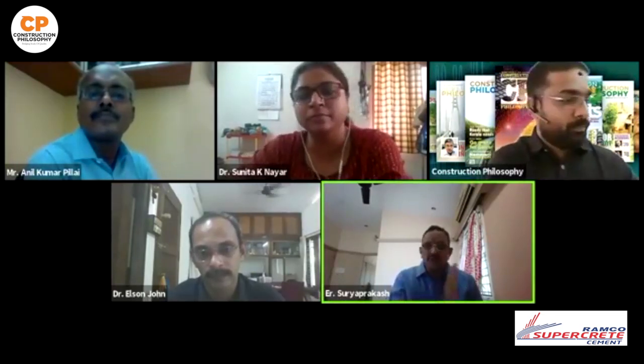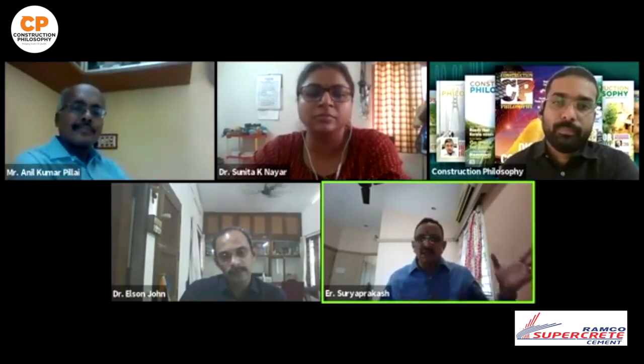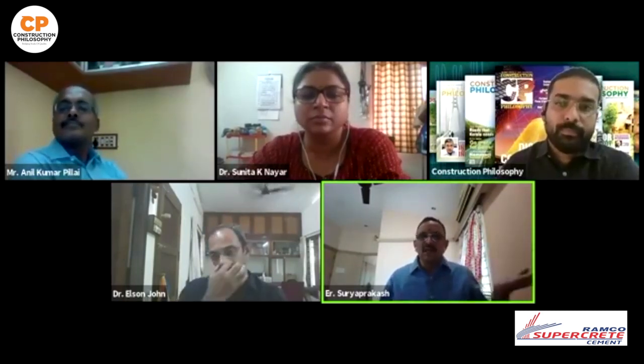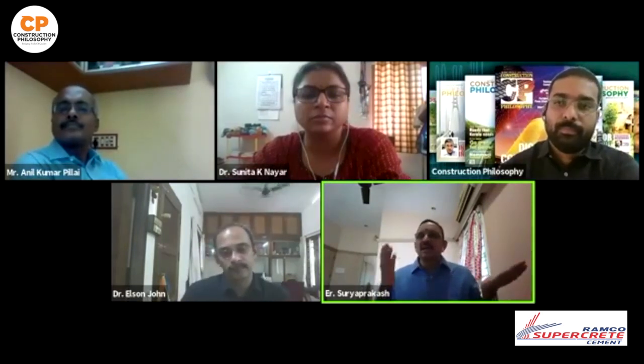Mitigation of cracks is to prevent them. That means follow the quality process. Even if you follow the quality process, the problem can occur because of a mismatch between the environmental conditions assumed in the design and the environmental conditions at the site. Somebody also raised that point. So we have to mitigate such changes by incorporating them in the process. What should be the change mechanism in the mix design in case there is a difference in the site condition, number one. Number two is, in spite of all this, cracks occurred in the concrete.